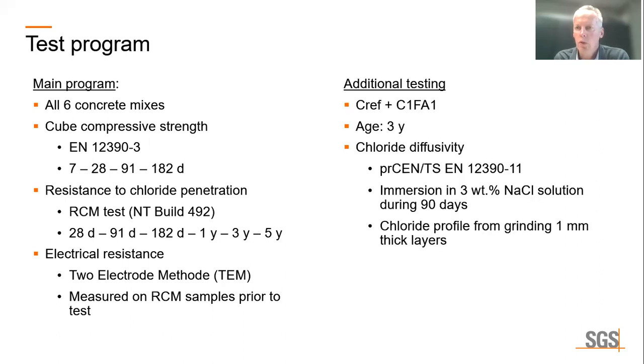Then additional testing was performed on 2 concrete mixes, the reference concrete and 1 fly ash concrete mix, at the age of 3 years. In this additional investigation, we have measured the chloride diffusivity following the European standard EN 12390-11. In this method, specimens are immersed in a sodium chloride solution during 90 days, after which a chloride profile is determined from grinding 1 millimeter thick layers.